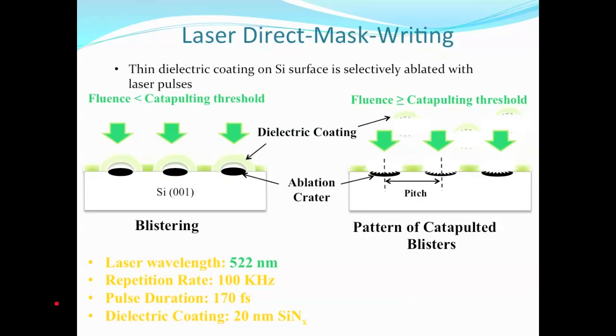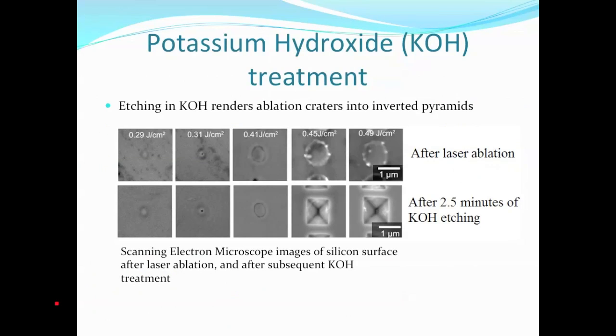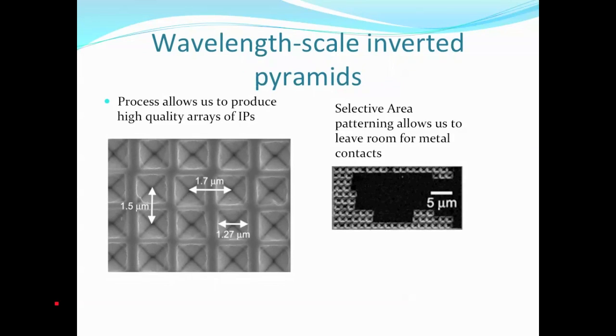Well, we coat silicon with a thin layer of silicon nitride and then apply laser pulses to the surface. When the laser fluence is below a catapulting threshold, the dielectric coating simply blisters. Once the laser fluence goes beyond the catapulting threshold, the dielectric coating is ejected and a crater is left behind in the silicon surface. Then we can treat these craters with KOH, or potassium hydroxide, and selectively etch pyramids into the craters. Using this process, we can fabricate very high-quality arrays of inverted pyramids for light trapping. As well, we can selectively pattern the area of our solar cell.